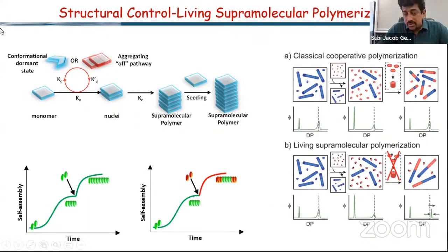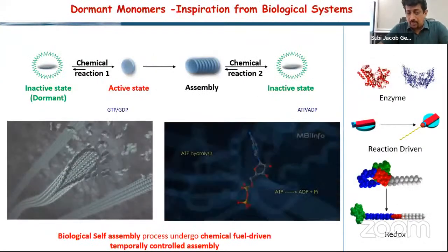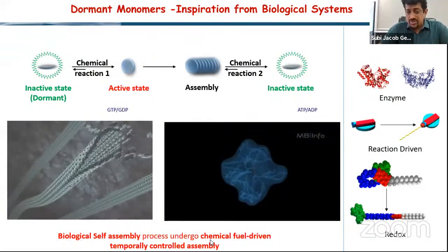One of the ways is, taking a cue from ATRP reactions, where a dormant state was introduced at the propagation step; here, a dormant state was introduced at the nucleation step. So what you want is a controlled nucleation. Once you have that controlled nucleation, you can get structural control in the system, and then we can come up with different monomers and get multi-component structures. This is the way living supramolecular polymerization has to be addressed. But we have come up with a slightly different approach to address this entire system. I would say this was our major contribution in the last 5 years.